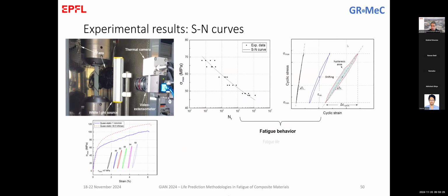Coming back here, you can use these data points to plot these cycles, with 20, 30 points, depending on the accuracy that you want. So you see already the complexity of data handling. Here is again the question about the capacity of the machine, as Professor Bedi mentioned before, the capacity of the recording device to record data so fast, the capacity of your camera, this video extensometer camera, the frequency of photos that this camera can take, so that it gives you directly the measurement of the strain.